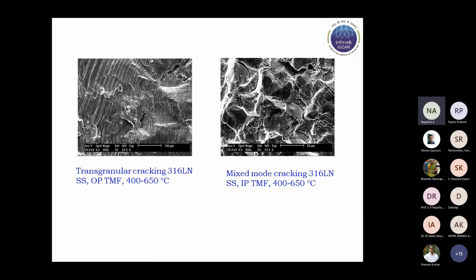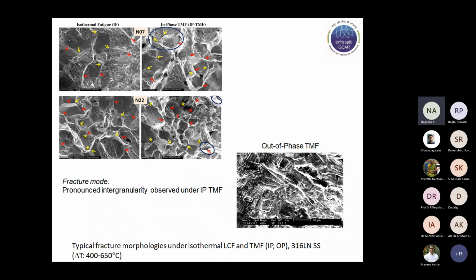And the creep damage happening under in-phase cycling was reflected in the form of extensive grain boundary cracking induced by the creep damage. The OP cycling resulted in a pure transgranular cracking without much creep damage. Whereas there is a mixed mode, largely dominated by creep cavitation kind of damage, under IP, in phase TMF.